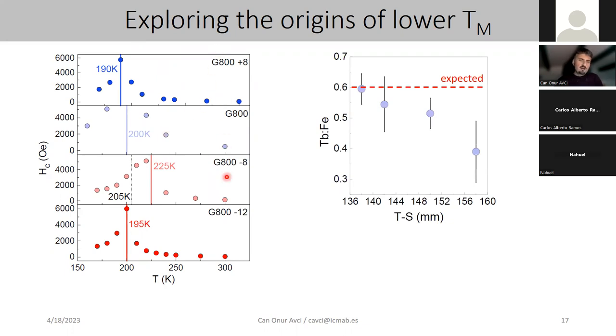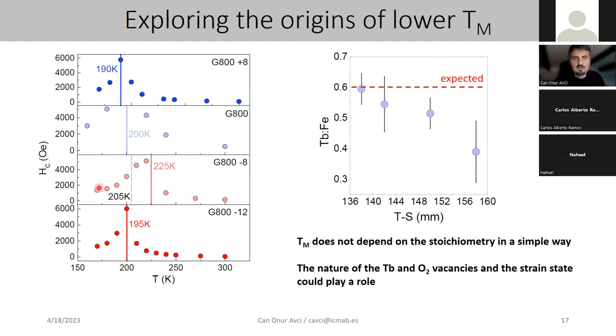And we said, okay, are we really changing the stoichiometry this way? To test this, we did some XPS measurements, and as expected, we saw that when we decreased the target to sample distance, we get closer to the bulk value, which is 0.6, the terbium to iron ratio, the expected value. Despite this very clear, convincing trend of changing stoichiometry with the target to sample distance, we did not see any clear indication that this anomaly in the compensation comes from the stoichiometry.